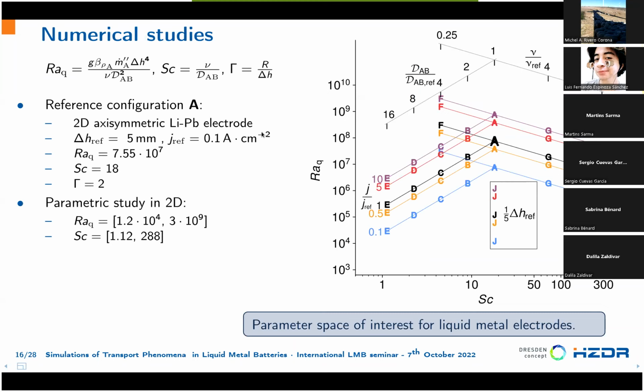So to study the problem, we start from a 2D axisymmetric lithium lead electrode because we know very well the material properties for this alloy. They are well known due to the other application of this alloy. And we study a 0.1 ampere per square centimeter configuration that is really in the regime of interest.